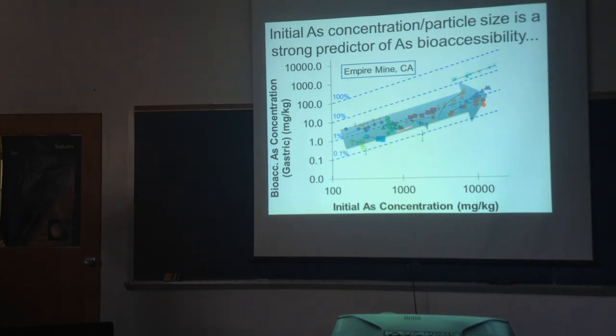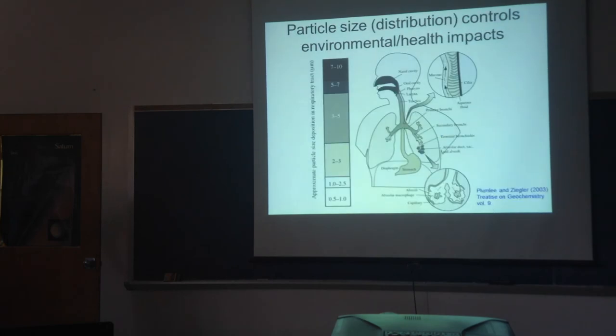But we see this overall increase of bioavailability with higher arsenic concentration, but it tends to be clustered around this 1% bioavailable. That's kind of the typical amount. But again, some of these samples are more than 10% bioavailable, and others are lower. So we still see that range, but there's this overall correlation. As I mentioned, these very fine particles are the ones that penetrate down into the lungs, and this is why particle size is really important to understand in terms of environmental fate.